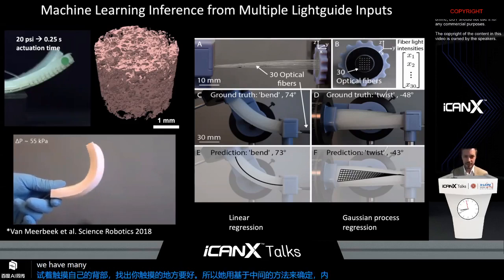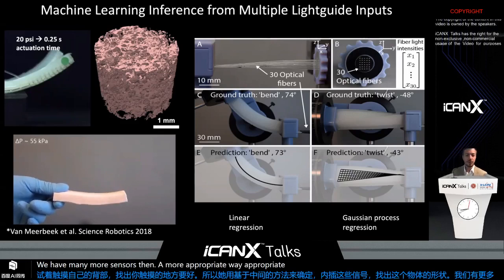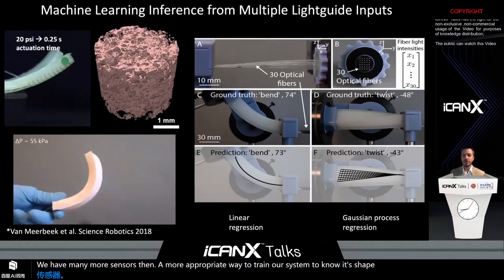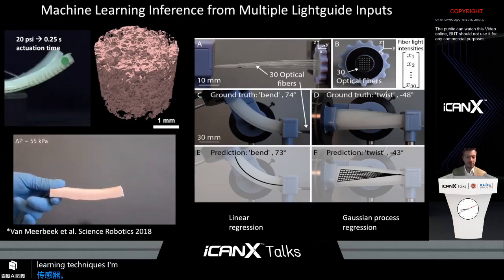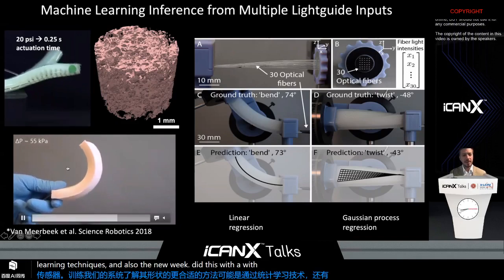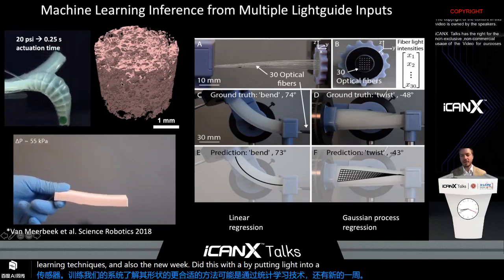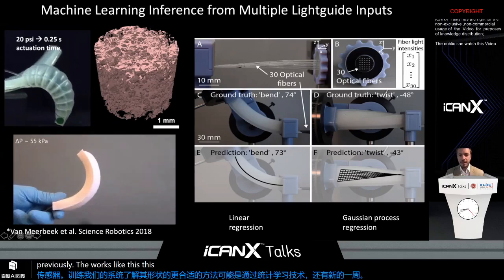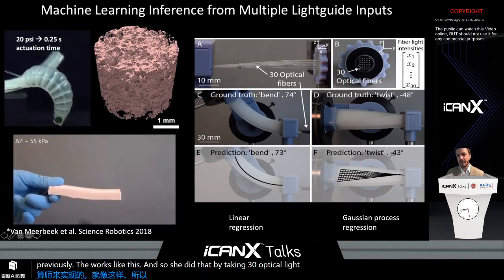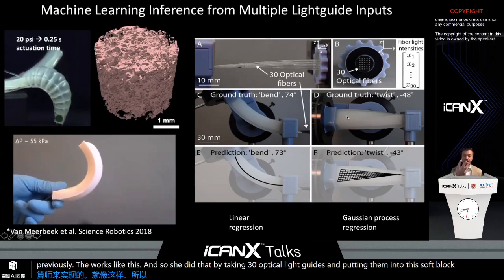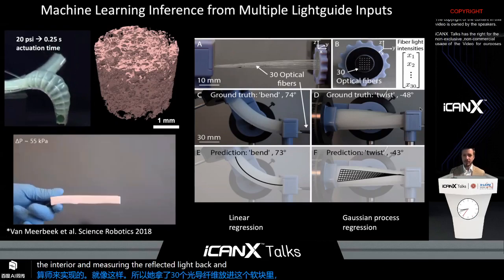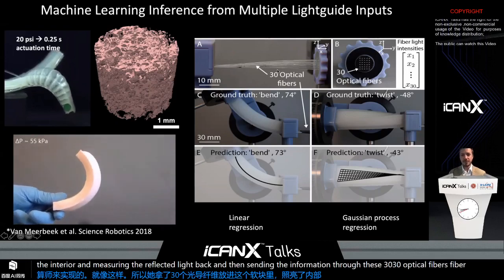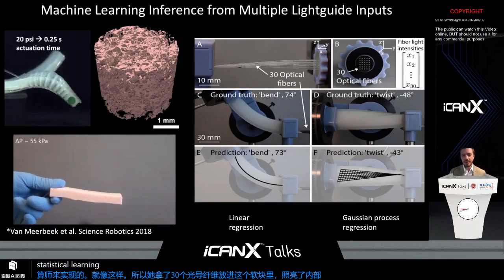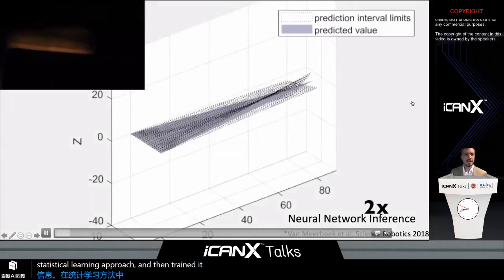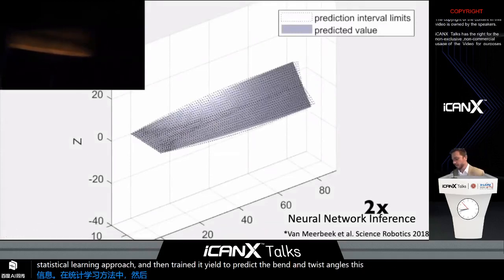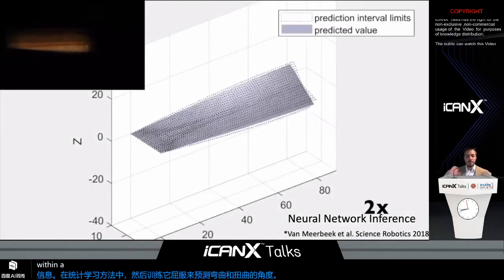If we have many more sensors, then a more appropriate way to train our robot or system to know its shape is probably through statistical learning techniques. Ilse van Meerbeek did this by putting light into a foam-based fluidic actuator that we made previously that works like this. And so she did that by taking 30 optical light guides and putting them into this soft block, illuminating the interior and measuring the reflected light back, and then sending the information from these 30 optical fibers into a KNN statistical learning approach, and then trained it to be able to predict the bend and twist angles of this foam. And it was quite accurate to within the boundaries of the light guide.